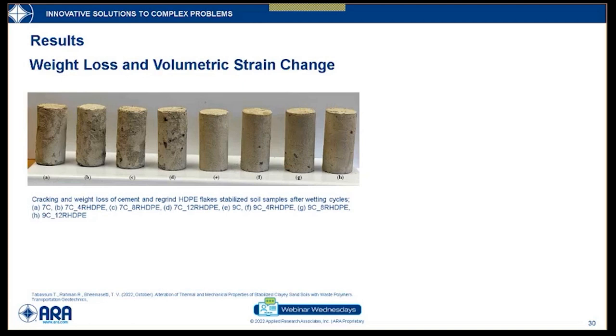The results show that on the very left-hand side, the four soil samples have more weight loss, like the soil is losing material due to the repeated wetting cycles, and these four samples are mixed with low cement content, that's 7%. But on the right-hand side, the four samples show the soil when treated with 9% cement and different doses of plastic. So it is very clear that when mixed with low doses of cement contents, the soil samples lose more of their weight than with the higher doses.